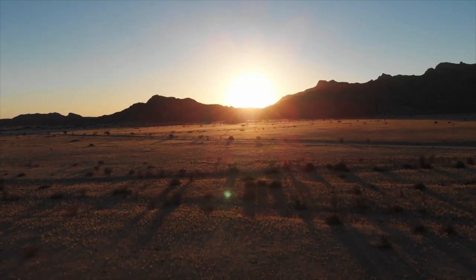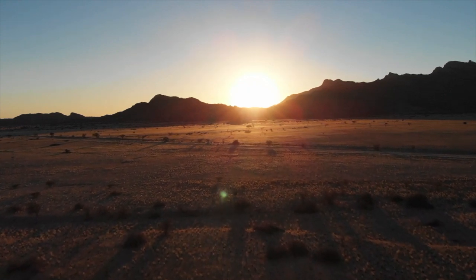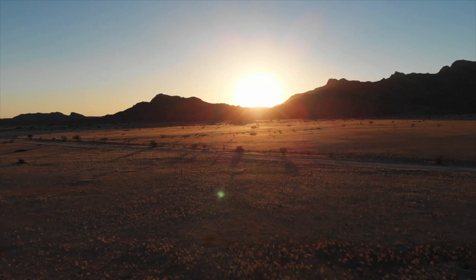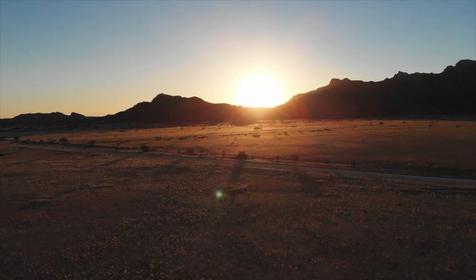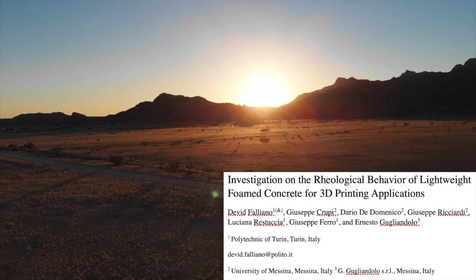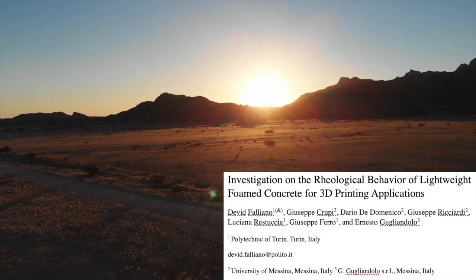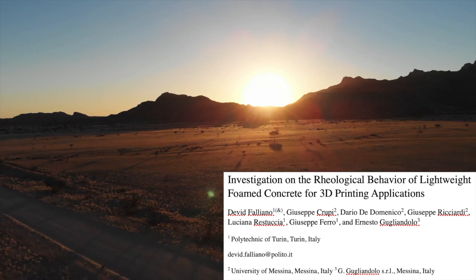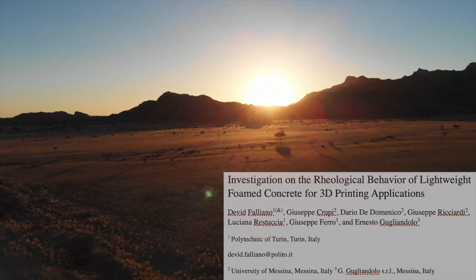Lightweight foam concrete is becoming more common because of how easy it is to use, but in order to use it for 3D printing, it would need to be extrudable. Extrudable lightweight foam concrete would be great for 3D printing because of its thermal insulation and acoustic qualities, in addition to fireproofing. In this study, the target dry density was 800 kilograms per meter cubed because that was figured to be the best balance between strength and staying lightweight.